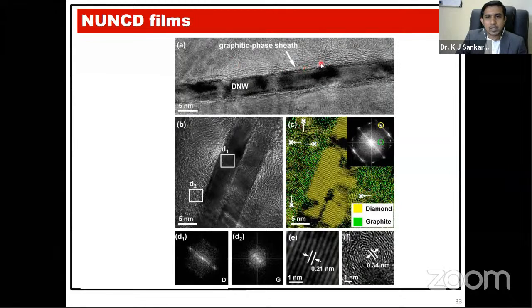How to confirm this is graphite? So this is the colored high resolution TEM image, and you can find this is the diamond nanowire. The yellow region is the diamond nanowire, and the green regions show the graphitic phases. These graphitic phases are really conducting in nature compared to the diamond, because this is sp2 hybridization and diamond is sp3 hybridization. The d-spacing of diamond is 0.21, which is taken from this region, and from this region we took the d-spacing of 0.34, which represents the sp2 graphitic phases.